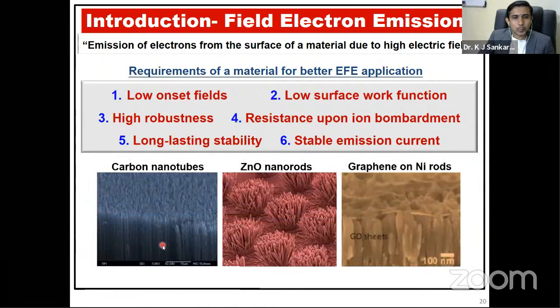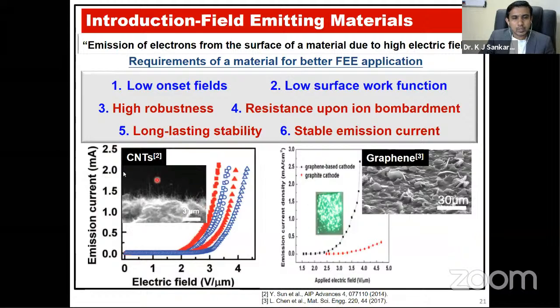People have used so many materials. Out of that, carbon nanotubes, zinc oxide nanorods, and graphene produce a very low onset field. These are very famous field electron emission materials that can go for real applications. But there are many drawbacks from these materials. Carbon nanotubes can emit electrons with a low turn-on field. Also with graphene, you can see the turn-on field is nearly around 2, and it can achieve a low onset field and low surface work function.